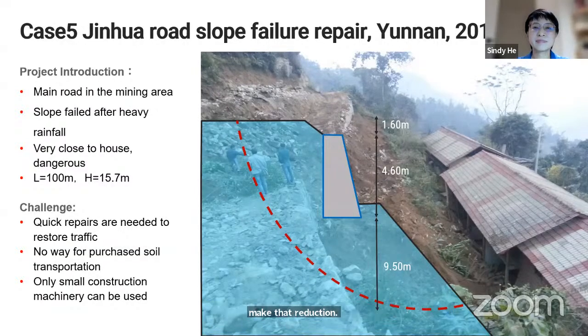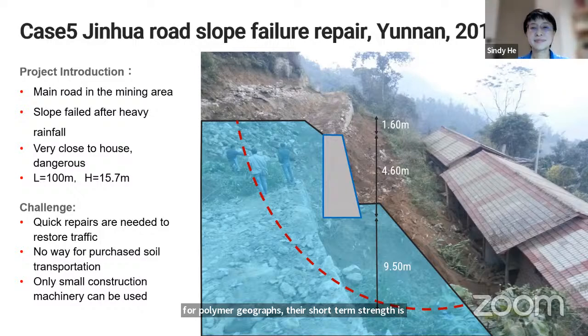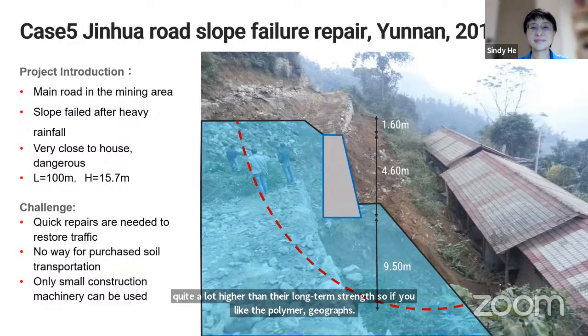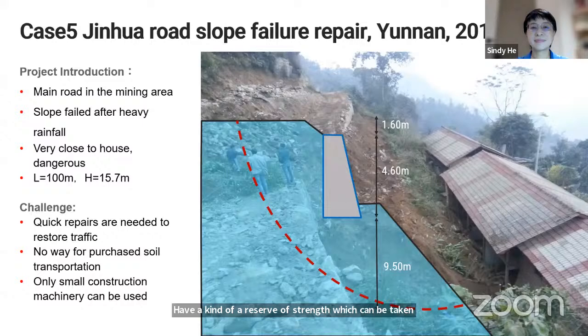But on the plus side, especially for polymer geogrids, their short-term strength is quite a lot higher than their long-term strength. So if you like, the polymer geogrids have a kind of reserve of strength which can be taken into account during the very short-term loading from earthquakes. So they have quite some big benefit. In fact, that makes them rather efficient for designing these structures. So Sindy, a little bit about case 5.